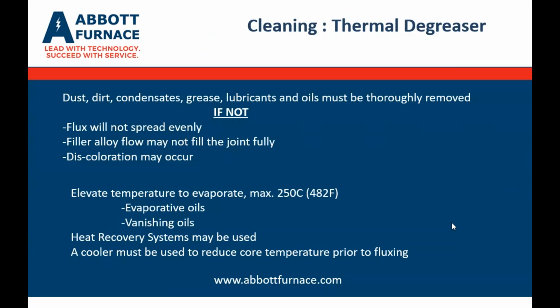The purpose of the degreaser is to clean the part, remove the dust, dirt, condensates, grease, lubricants, and oils that have maybe been applied to the fins or tubes in your upstream manufacturing process. Those parts need to be very clean, otherwise the flux will not spread evenly throughout the heat exchanger and into the joint. The filler alloy flow may not fill the joint fully, not giving us a complete brazed joint.